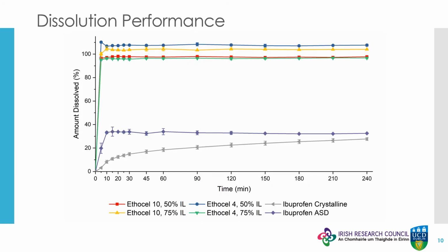As a demonstration of the improvements over amorphous solid dispersions, dissolution tests were carried out in deionized water. Here, it can be seen that all the powders containing the IL form of the API greatly outperform both the crystalline form and an analogous ASD, even when contained in a water-insoluble polymer. Full or close to full release of the API can be attained with all loadings and is irrespective of polymer